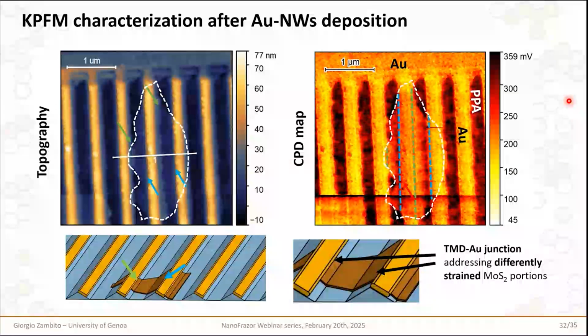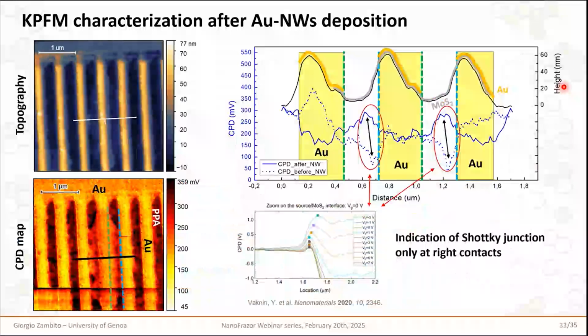But the interesting thing is that now we have created metal nanowires that are lying on certain facets, on certain regions of MoS2. And this MoS2 is locally strained on the left facets. So basically, these metal nanowires are addressing portions of the flake which are differently strained. And this will have an effect on the nature of the junction that we are creating between the flake and the gold.